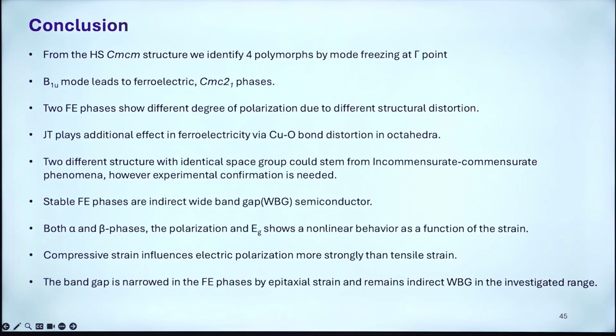That is the bottleneck for the experiment, because normally experimentally they measure Raman. If you do a temperature dependent Raman, for example, if it is a B2G mode, then you can see a shift in the peaks which will correspond to the softening which we see in this phonon. But here it is a B1U mode, so experimentally they should look into infrared, I think terahertz kind of measurements. That's what I am not an expert in.